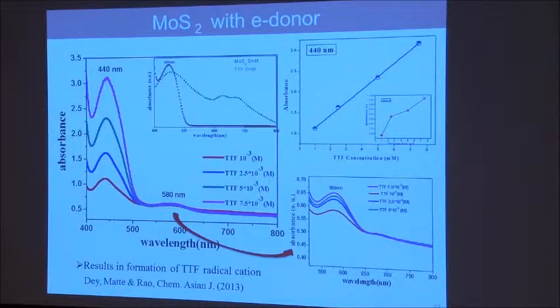You can dope electrons by putting tetrathiafulvalene. We tried to do the same thing with molybdenum sulfide. Here's a surprise: when they tried to put tetracyanoethylene, which withdraws electrons, it had no interaction with MoS2. The reason is MoS2 is a p-type semiconductor.